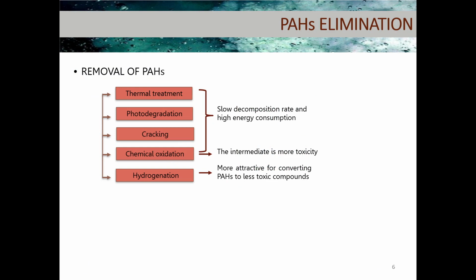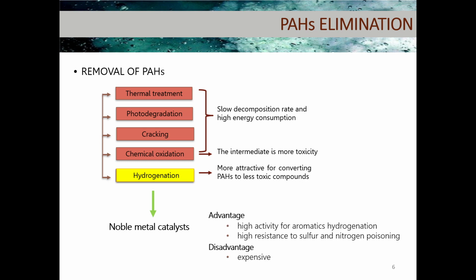We have processes to eliminate PAH, such as thermal treatment, photodegradation, cracking, or chemical oxidation. But these processes show a slow decomposition rate with high energy consumption. Chemical oxidation can also produce intermediates with higher toxicity that can dissolve in water resources. So hydrogenation is the suitable method to convert PAH into less toxic compounds, and this process requires a metal catalyst. The noble metal catalyst has high activity for aromatic hydrogenation and high resistance to sulfur or nitrogen poisoning, but it is expensive and limited for large-scale application.